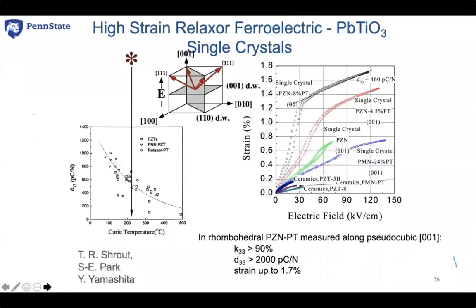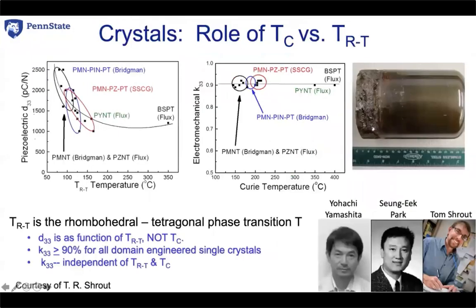Another major contribution to the field has been our understanding and the development of high-strain relaxor ferroelectric lead titanate single crystals. You see here original work from Yohachi Yamashita, Tom Shrout, and Seung-Eek Park, where they were able to demonstrate that if you took 50 years of d33 as a function of Curie temperature, that was kind of the published literature until their work, they were able to demonstrate that you could massively increase the available piezoelectric coefficients by using relaxor ferroelectrics.